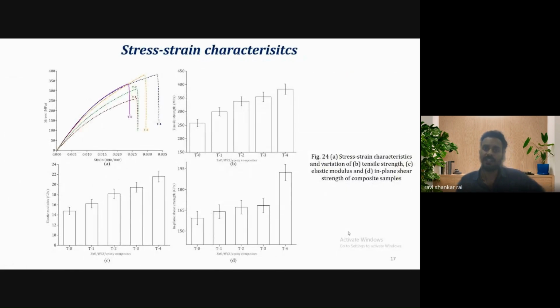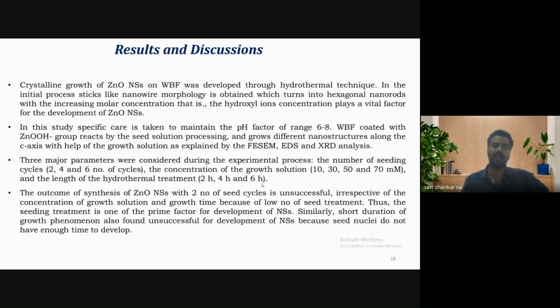The stress-strain characteristics of the sample have also been checked, and it was found that as the ZnO nanostructure increases, the stress-strain characteristics improve: tensile strength increases, elastic modulus increases, and in-plane shear strength increases. So adding ZnO nanostructure inside the plain basalt fiber reinforced polymer composite is a better way to achieve high mechanical characteristics. The results and discussions are: crystalline growth of ZnO nanostructure on woven basalt fiber was developed through the hydrothermal technique.